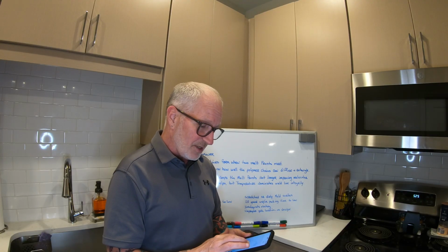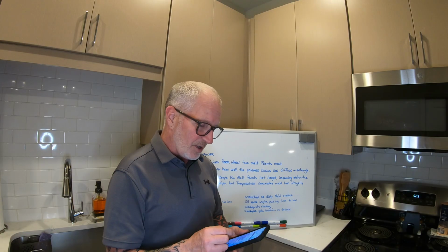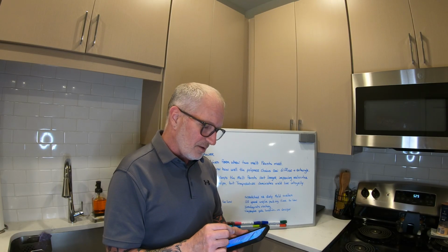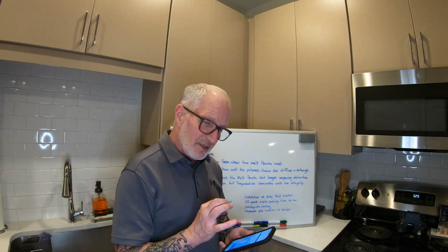So on the material side, what you'd look at is check the material for contamination, check material for moisture, check for uneven material temperature, or use a higher melt index if possible. Okay, that is for the material.